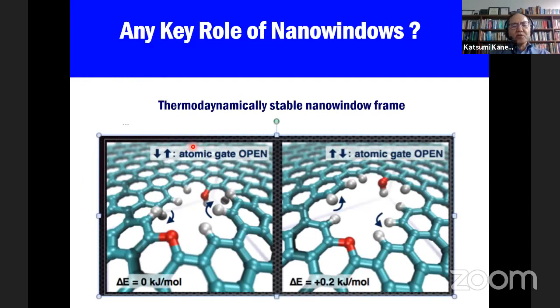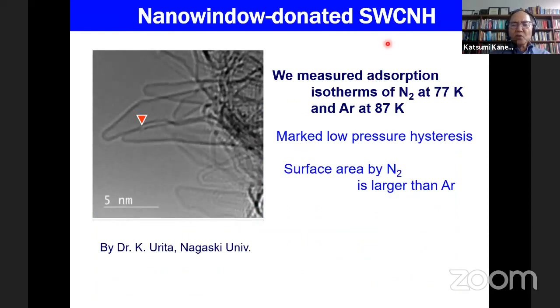We say window, not pore, because we cannot store molecules here. Just penetration occurs, a very different function that nano windows have from the pores we ordinarily talk about. In a real case, for example, single-wall carbon nanohorn, we donate a nanoscale window. Very recently, we are just writing the paper, we put a phthalocyanine molecular catalyst here. In such a case, the nano window size is regulated to nearly 0.4 to 0.45 nanometers. Then we can control the density of the window size. So this technology should be applicable in future.